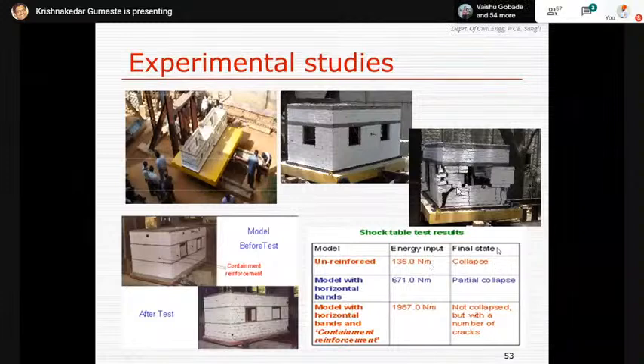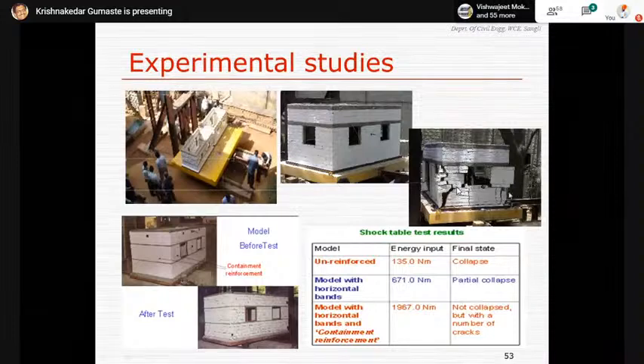And you could see there was a complete collapse of the unreinforced model, which is not there in the figure. But for the model with horizontal bands, the lintel band that was given, you could see the energy input at collapse. There was a partial collapse, whereas the unreinforced element collapsed completely. However, the amount of energy absorbed by this model was about 671, which was about 5 times larger than the unreinforced model. Whereas the model with horizontal bands, which had containment reinforcement also, the energy absorption